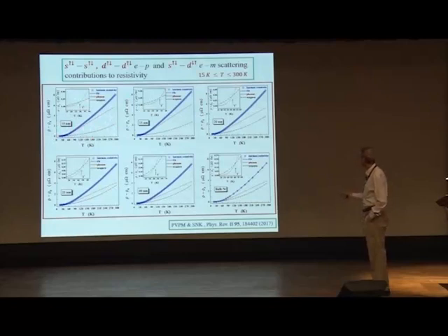But when you increase the crystallite size, they become comparable, so that gap is reducing between them. What is happening more is that the phonon part is getting suppressed, while the magnon part does not change very much. You can check that even with crystalline nickel. That is a bulk case I have put here for comparison. And there is a temperature at which these two contributions are the same, the so-called T star.